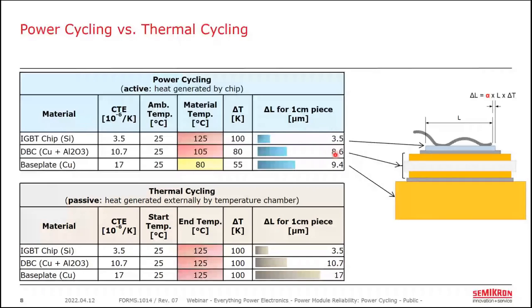On the other hand, the copper base plate down here will not reach the same temperature as the IGBT chip and might only see a 55 Kelvin rise above ambient. Since copper still has a larger CTE than silicon, there is a larger change in relative length.